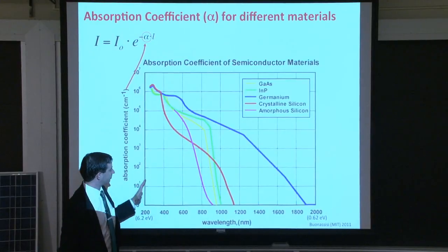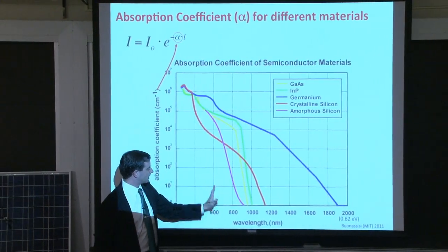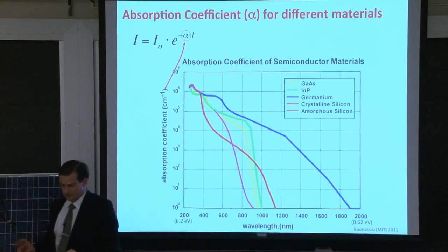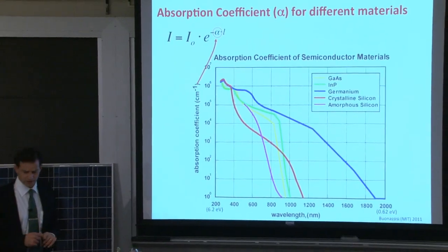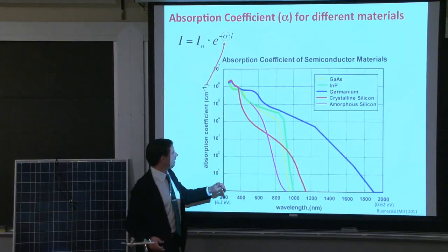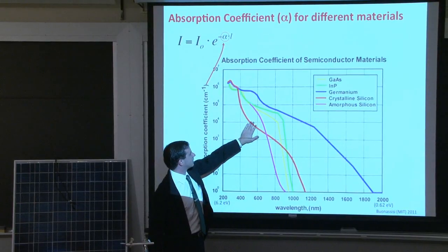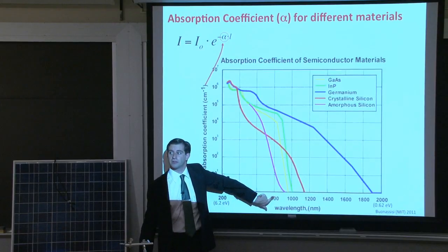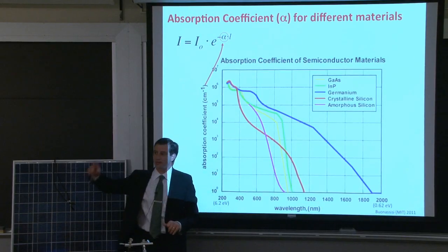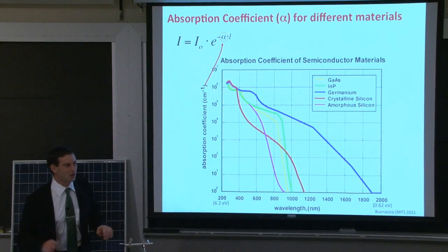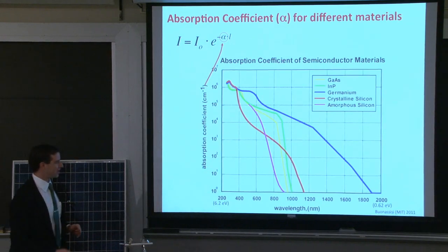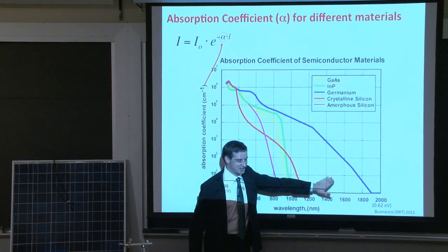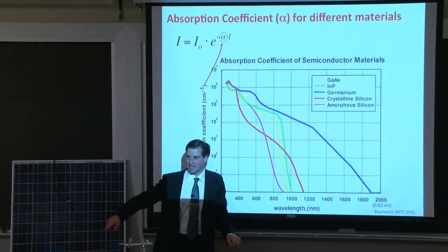And there's a lot of solar radiation right around 550. So the numbers that I have off the top of my head work out to be on the order of a micron, a little less for gallium arsenide, and somewhere on the order of 10 microns or so for silicon. But now if we go out to 800, there's still a lot of solar flux out there. If you recall the solar spectrum, as the folks have been doing their homework, there is still a lot of flux around 800. It continues all the way out to here, although decaying in intensity, a la black body.